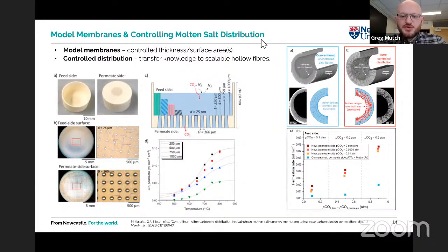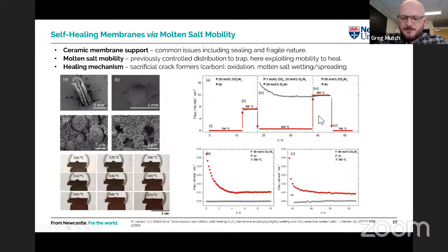As I said, these model structures are no use for a real application, but we can take this knowledge and apply it in a structure that is useful. So this image here is a ceramic hollow fiber. Just think of a very small, like a plastic drinking straw structure. We use the knowledge from here to build a better membrane. So you see on the image on the left in the blue, we have a very, very low surface area for desorption due to the way that we've filled the structure with carbonates. We've filled all the porosity.